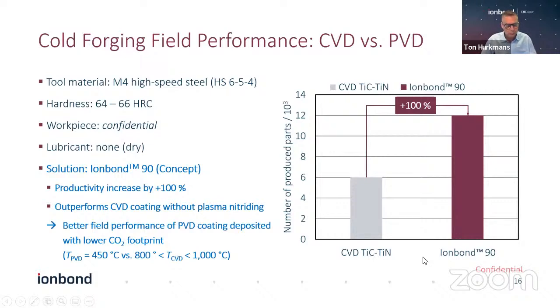But in the sustainability thinking, we process this coating at 450 degrees Celsius instead of 1000, so about half the temperature. So the energy consumption is much lower, and it isn't mentioned here, but also the processing time is typically for CVD about 24 hours at this temperature, where we process about 6 to 8 hours. So there's another gigantic saving in CO2 footprint in processing these coatings.